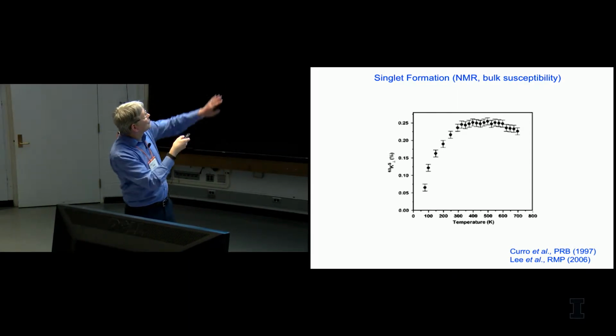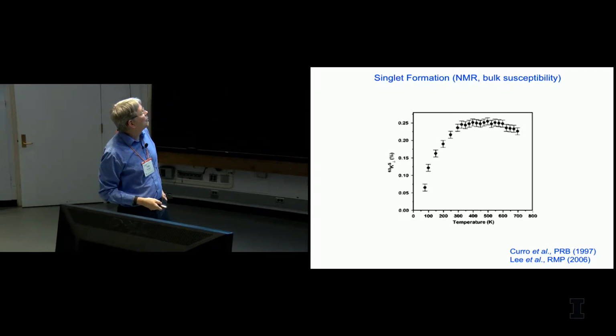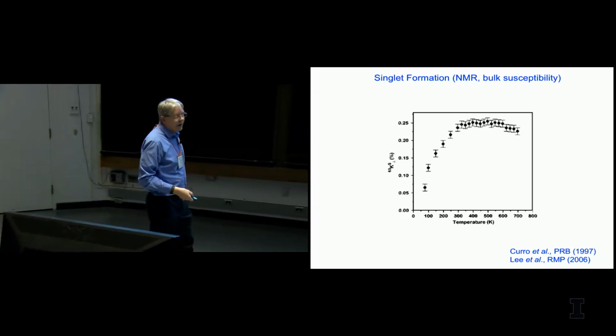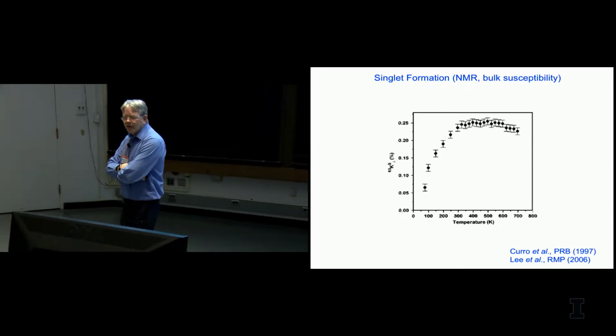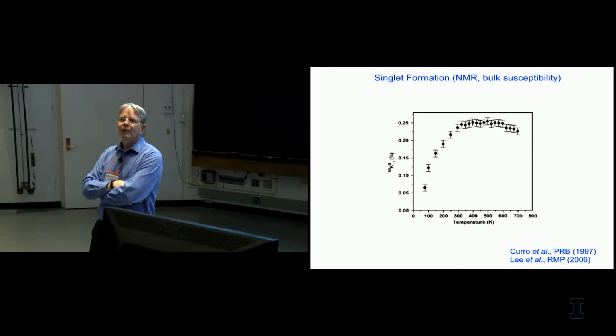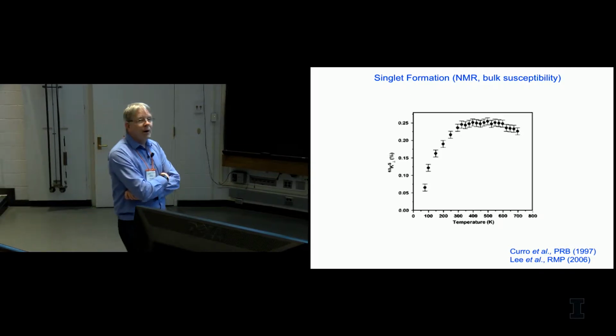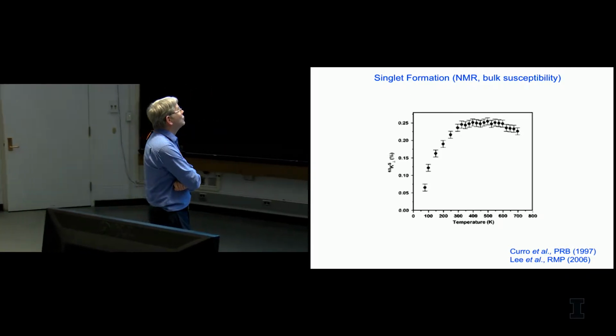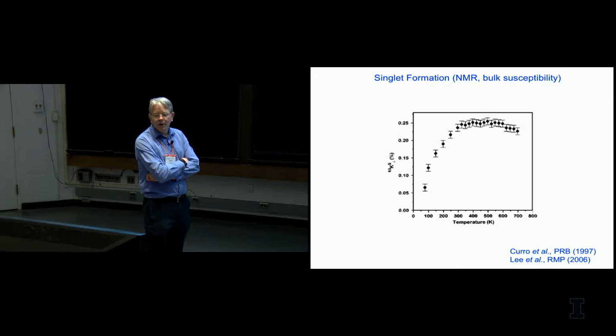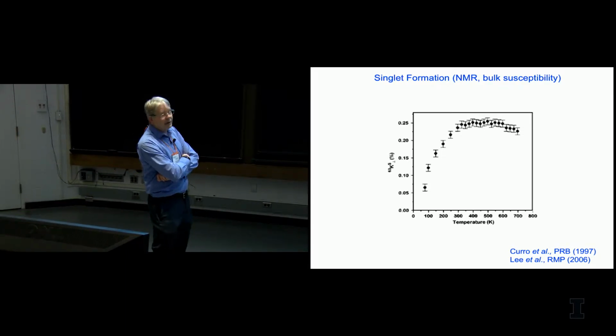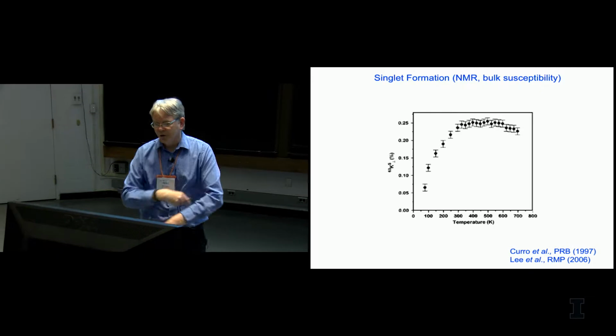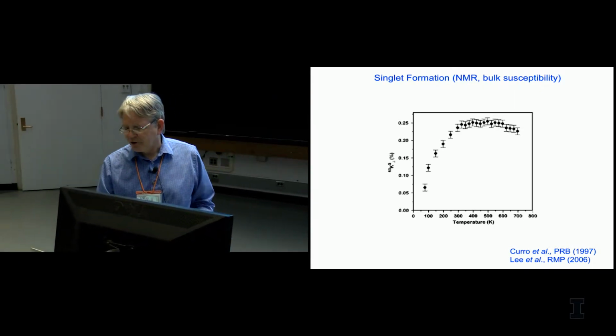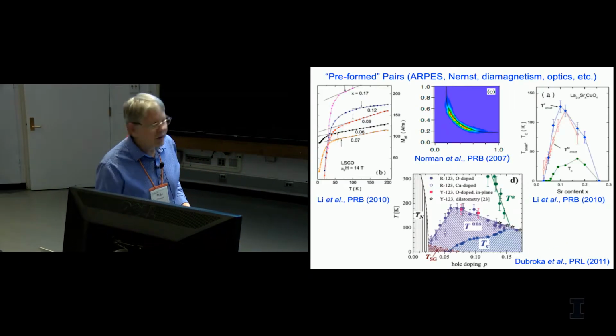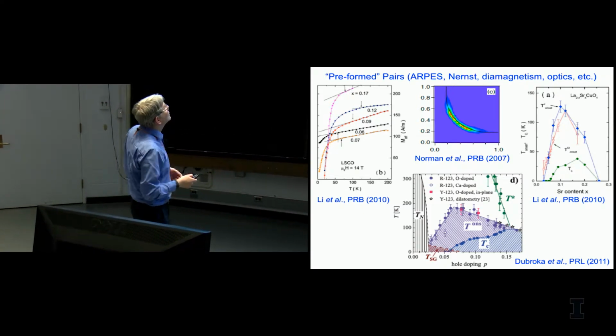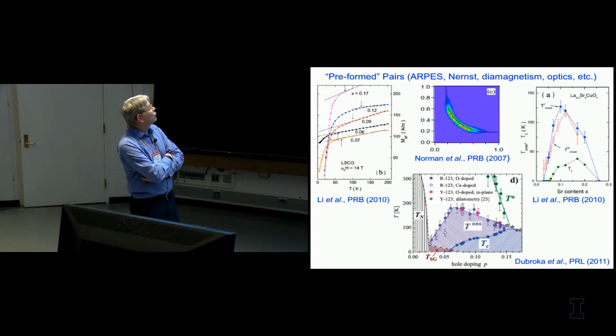Pointer's not working so great, but you can see at some temperature, the susceptibility starts to drop, which was sort of taken as evidence that either you were having antiferromagnetic spin fluctuations coming into play or that you had singlet formation, that is, the electrons or the carriers were starting to form singlet-type pairs and with a susceptibility that decreased. And this led to the possibility that people like Mohit Randeria and others talked about whether you actually had preformed pairs so that you may be sort of like what you see near Bose-Einstein condensation.